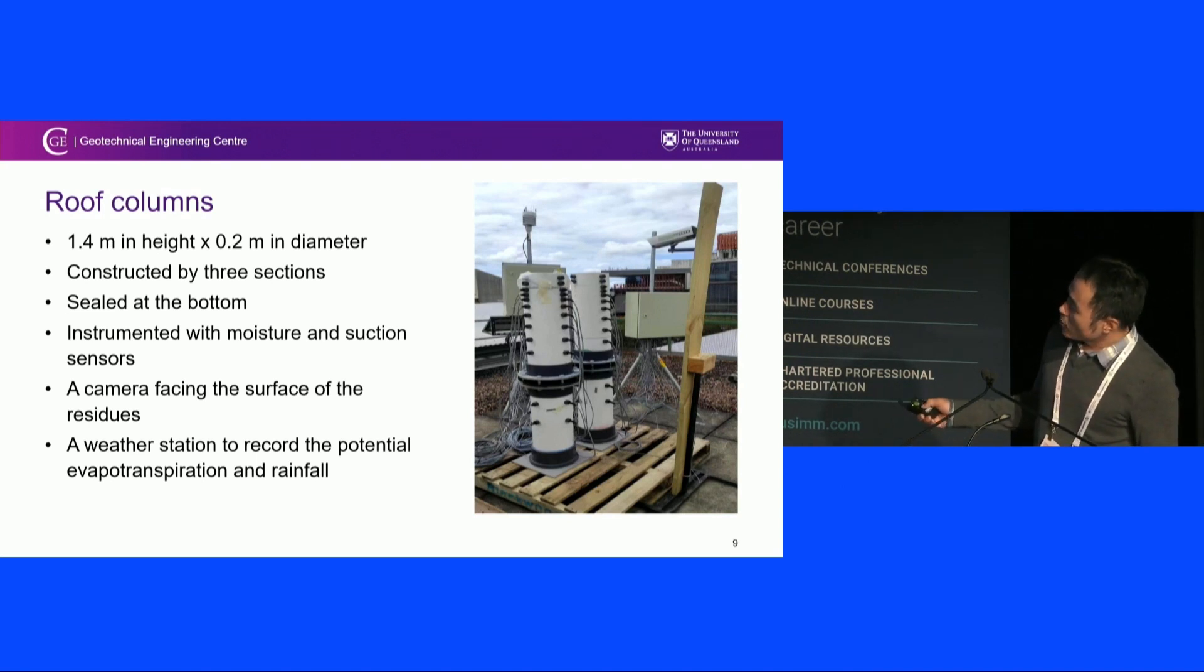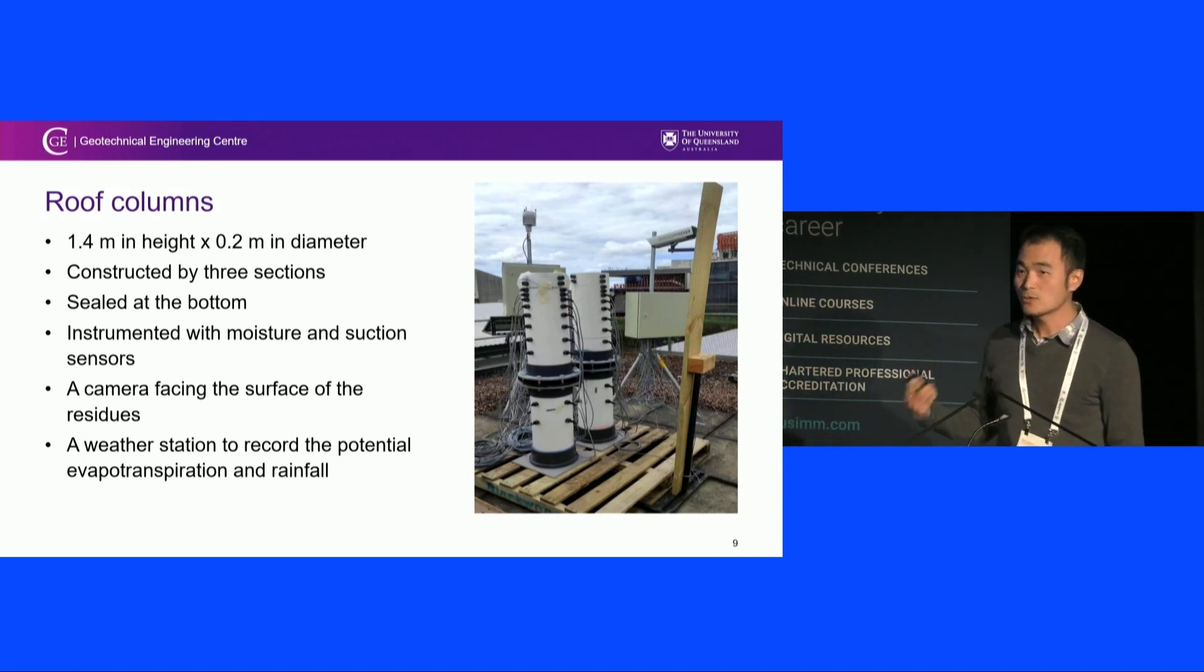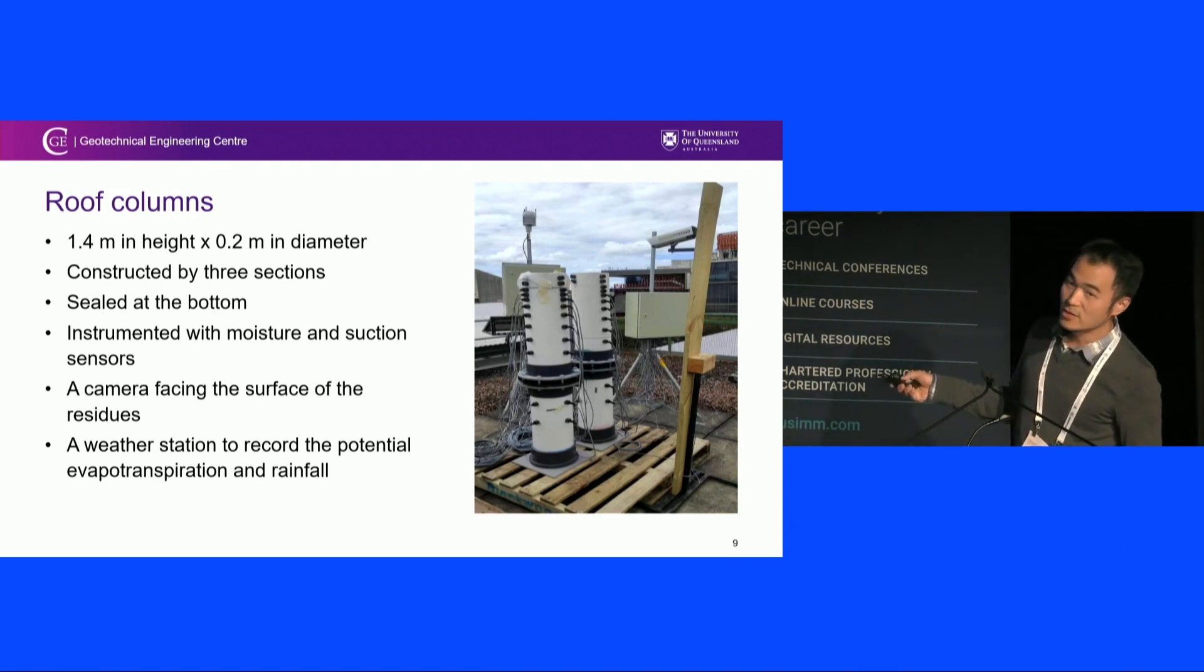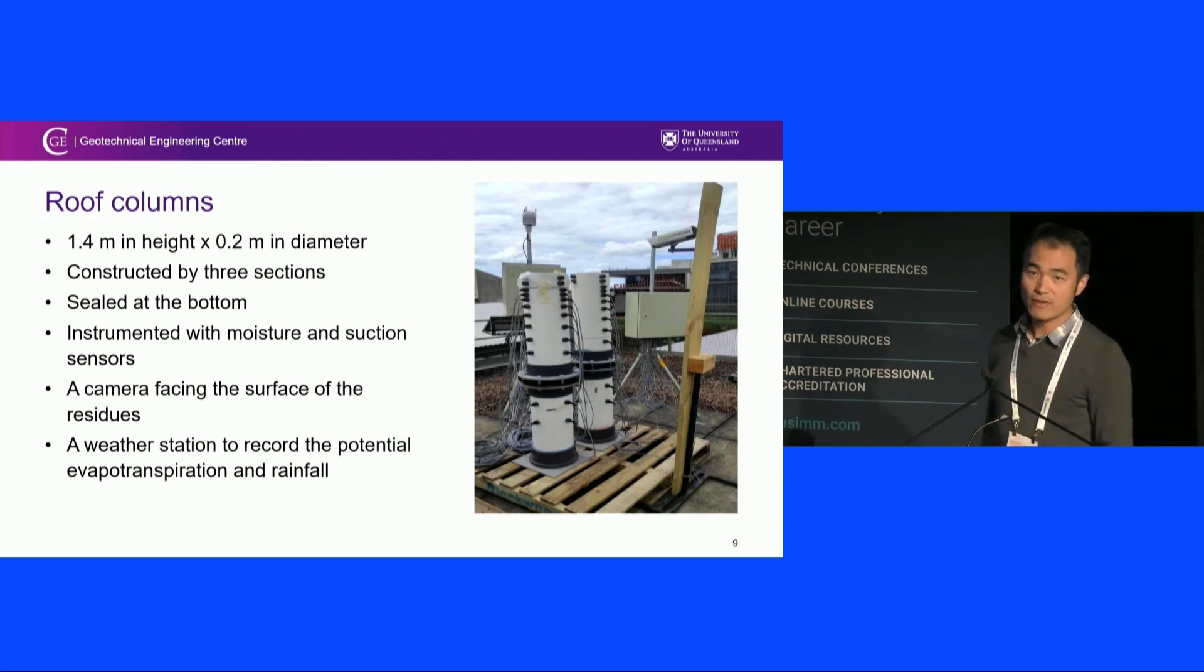We seal them at the bottom because the red mud is relatively low permeability, so the bottom leakage would be quite limited. But we could also have a drainage out to see how much leachate comes out. It was instrumented by quite a few sensors - particularly moisture and suction sensors - and has a camera facing the top to see the settlement, the cracking, and also the salt accumulations.